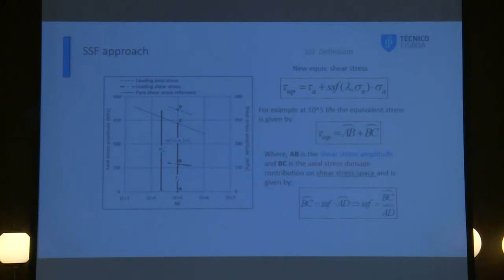If you take, for example, a fatigue life of 10 to the power 5, as you can see here in this graph, we want to compute the shear equivalent stress. We have here in the straight line, this is the reference, the pure shear stress reference is obtained by torsion uniaxial tests. We have performed around 10 uniaxial shear stress tests. That appears here. You obtain this curve. And then, we are going to compute AB and BC. AB is the shear stress amplitude that appears here. And then, we want to compute this distance, BC.